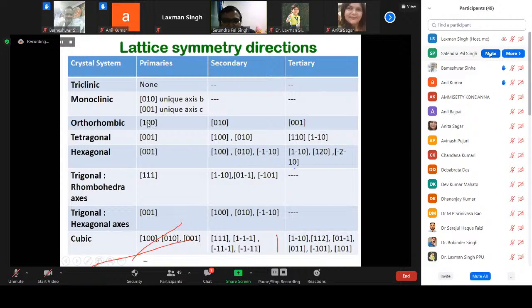In the orthorhombic, we have a symmetry axis along the primary, the secondary and the tertiary. All three axes will have symmetry operations. In the tetragonal, we have the symmetry along the 001 direction along the primary axis, 100 or 010 directions along the secondary, and 110 along the tertiary. Similarly, hexagonal has 001 directions, that is the direction of the primary axis, and so on. So this table represents the direction in which the symmetry has to be operated for the given crystal systems. All this is very important to understand crystallography; from a space group symbol, you can know the crystal system.